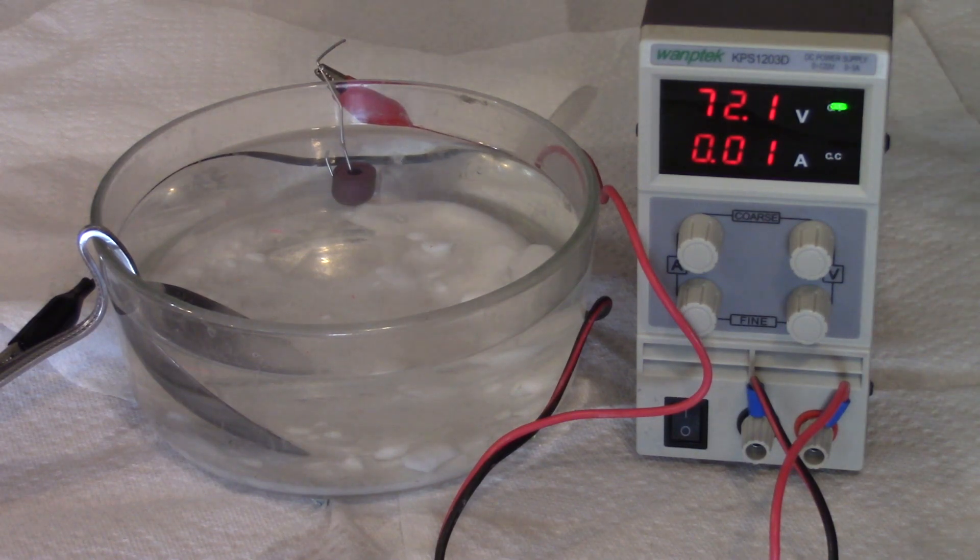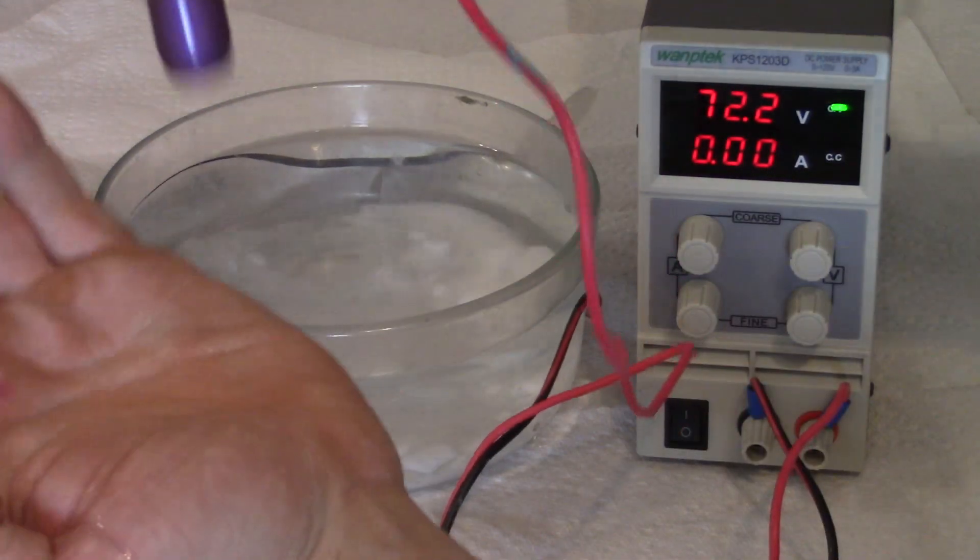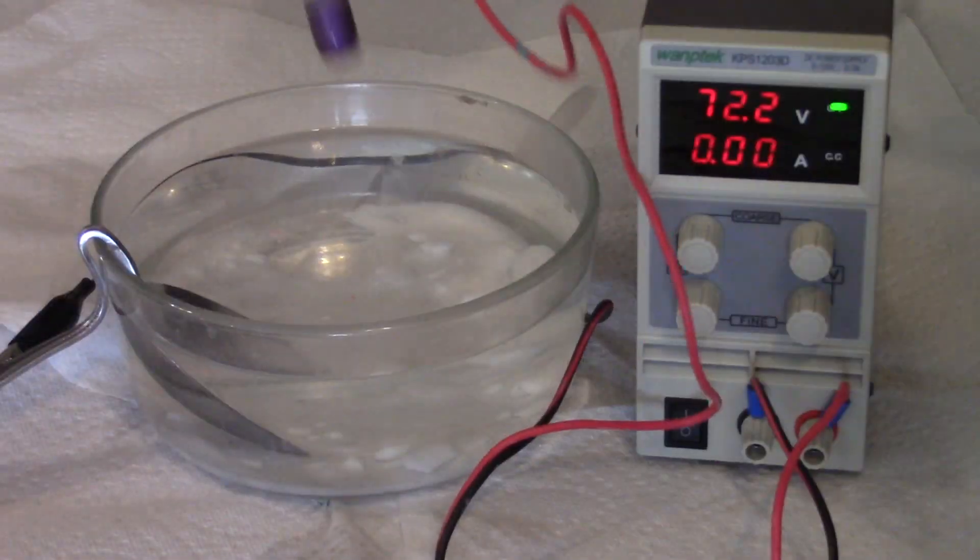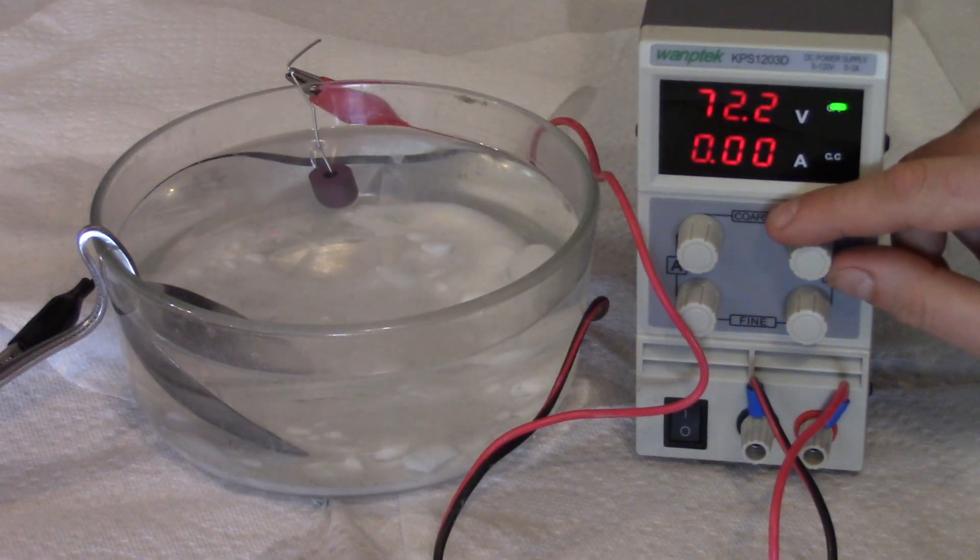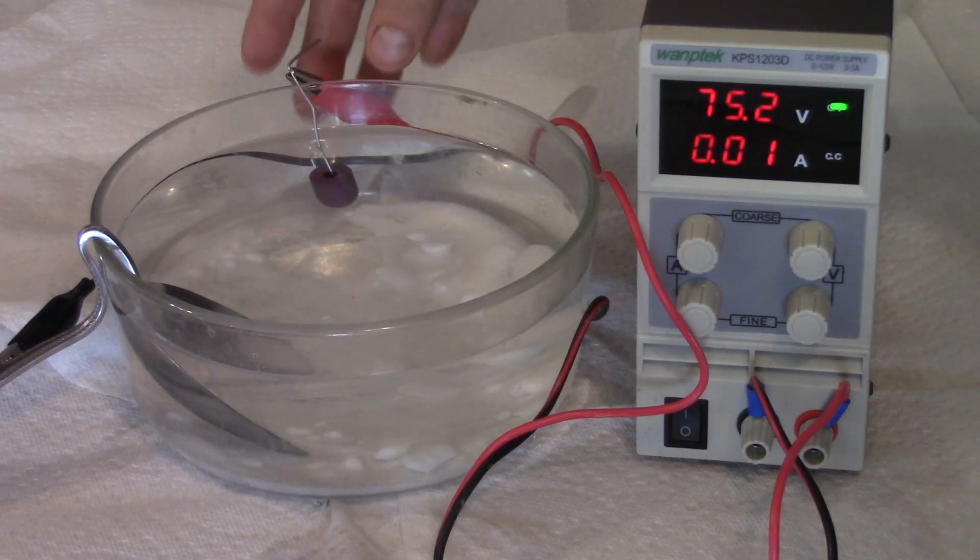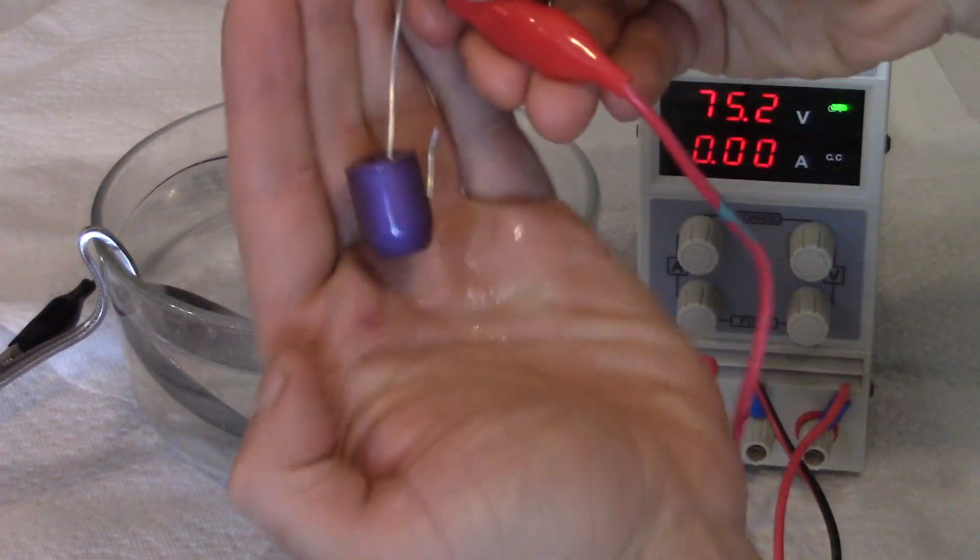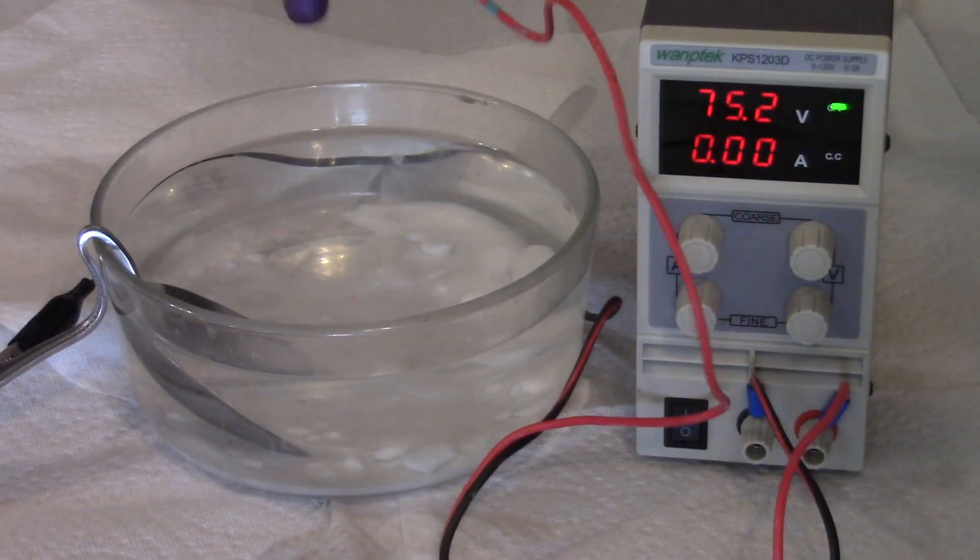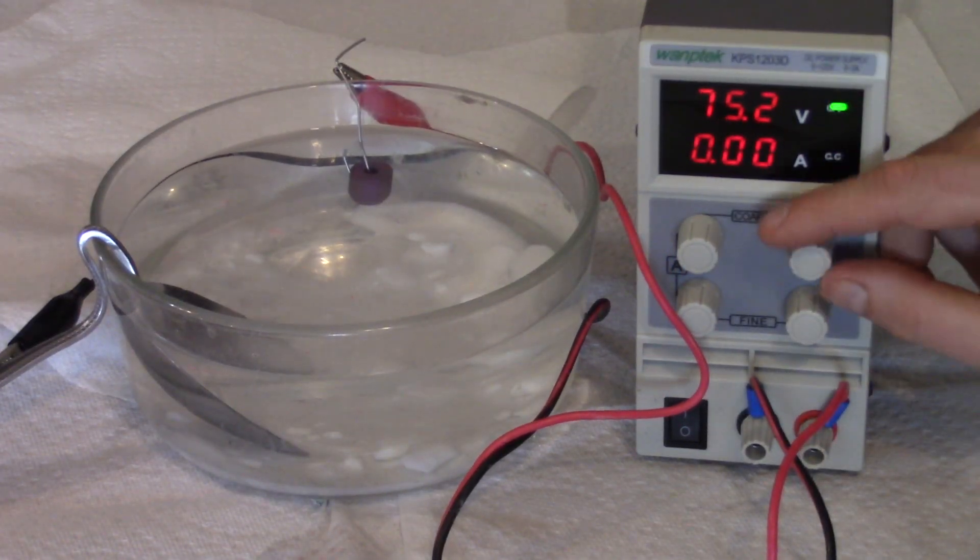I like that color, that's a cool color at 70. 72, once again very just a slightly different shade. Like I said before, most of the purples are all in these 70s. 75 if you want a real dark purple, but not like that dark purple we got at real low voltage. This is a much more in-your-face purple. Let's keep going up.